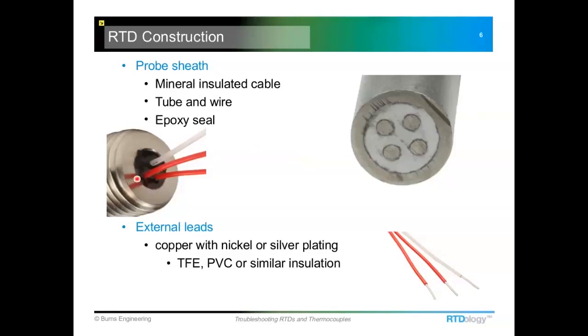preventing water vapor from getting inside the probe, and any other contaminants. It also provides some strain relief on those lead wires. One of the big failure modes for RTDs is to have moisture getting inside the probe, and that can cause a low resistance. We'll get into a little more detail on that a little bit later.